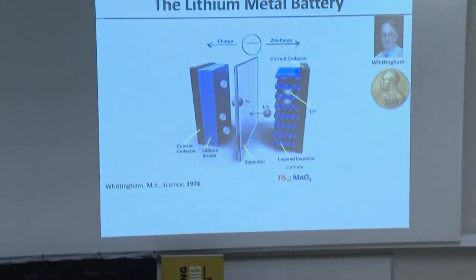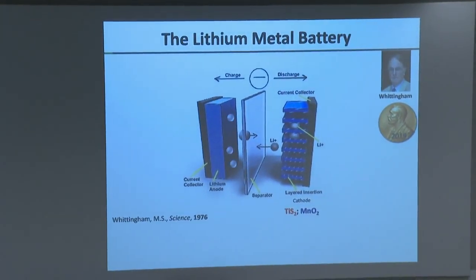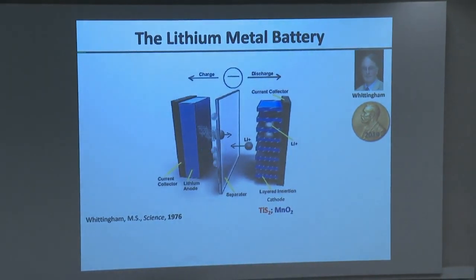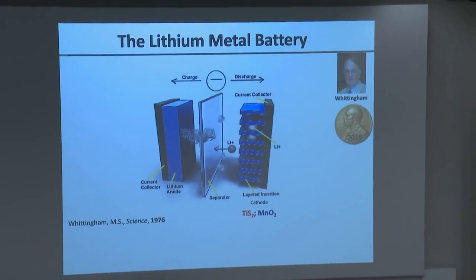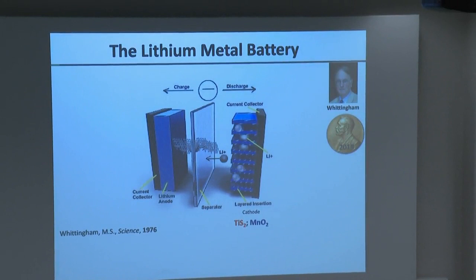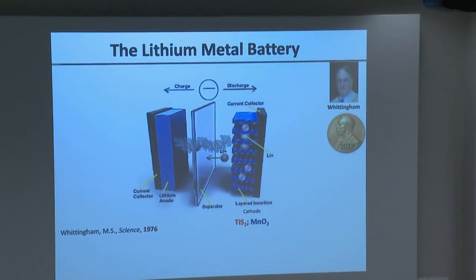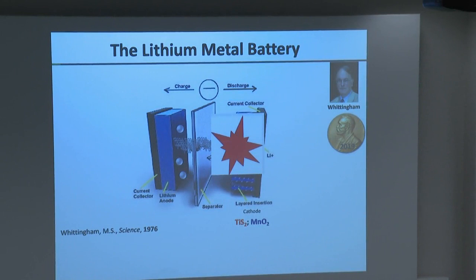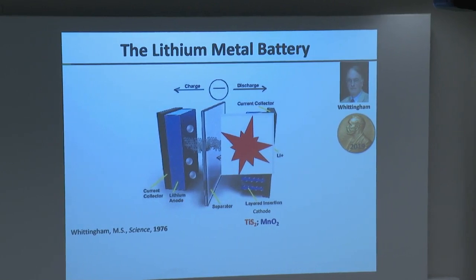So at first, everything is going great, okay? Charge, discharge, but then these structures, known as dendrites, begin to grow on the metal anode. They very easily pierce this polymer separator, cross over to the cathode, and short the battery internally. The ohmic heat generated as a consequence of that short is typically enough to ignite a liquid electrolyte in the space between the cell. So these things are a safety hazard, and no one will insure you if you put them in, say, an electric vehicle.